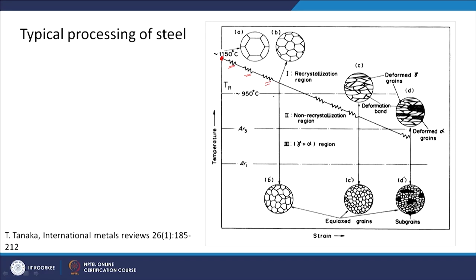So, this is a steel. Also the different critical temperatures are shown here, Ar3 is here, Ar1 is here, and this is around 950 degrees Celsius, above that is the TR region, which means where recrystallization can happen in the austenite phase. So, the first recrystallization region will be here. You start with a very coarse grain, then the recrystallization is happening. Then the temperature is continuously coming down, and this is a non-recrystallization region, that means there cannot be any recrystallization in this particular region. And then again you are putting a strain at different stages, and then the microstructure is something like this after